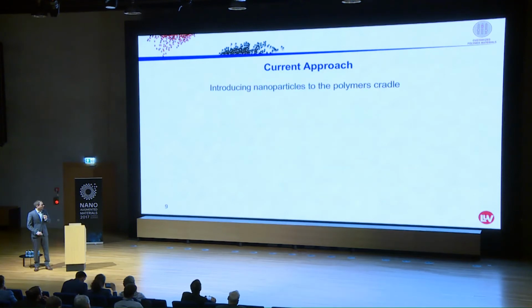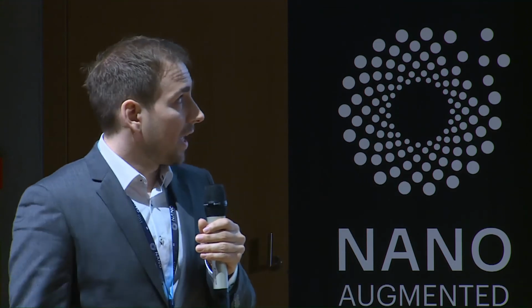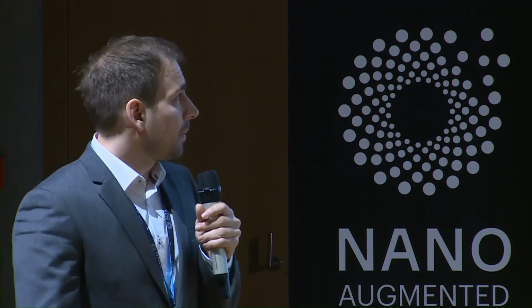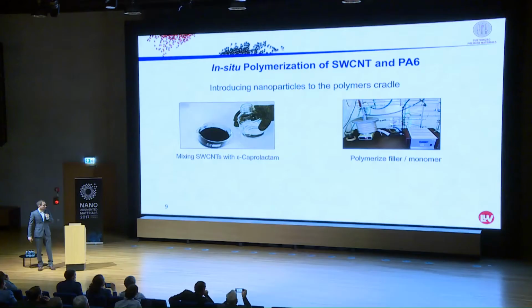My approach was to use a different incorporation technique. Not an extruder. I was using the in-situ technique. That means I'm introducing the nanoparticles to the polymer's cradle, so to the monomer. In the case of PA6, I mixed single-wall tubes, TUBALLs, with epsilon caprolactam. You can melt epsilon caprolactam at 70 degrees, and it's basically a liquid like water. So you can imagine there are pretty nice possibilities for mixing and dispersing it.